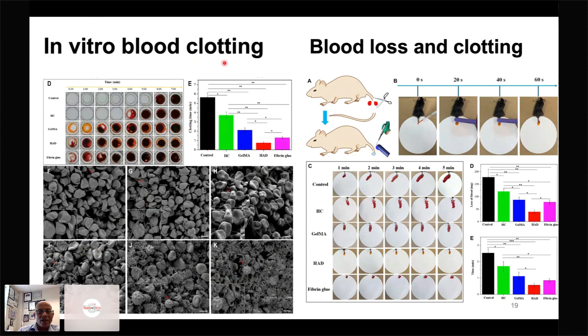This is an in vitro blood clotting assay, in a culture well. So this is a control where nothing is added to the blood. You just pipette blood into these wells, and then you look at, as a function of time, when they form clots. And then as you go down here, you can see that you have GelMA here, you have the hemostatic adhesive, which is our material, and then this is a fibrin glue. And so you can see that as early as 30 seconds in here, that's what you see in here, that the clot was actually formed.